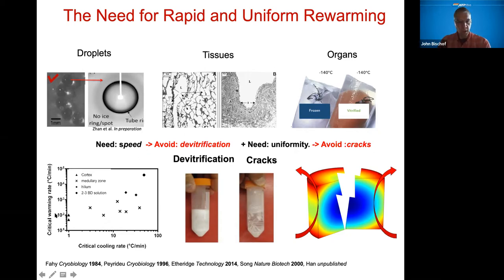But then if you look on the y-axis here, the critical warming rates, they're always 1 to 2 orders of magnitude higher than the critical cooling rate. And that's why he was really never able to bring back those organs. And it's still a rate limiting step today, because coming back in those large systems at 100 or 1,000 C per minute is essentially not possible. And so if you come back too slowly, you're going to devitrify. And if you come back too fast on the edges, you're going to crack.